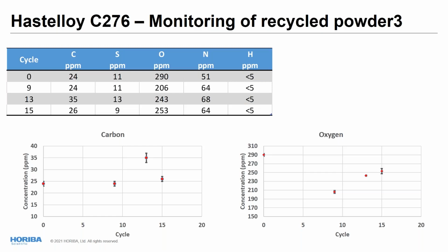There is an explanation. We needed to do some additional analysis, and we were not able to do them because we didn't have enough samples. But most likely what happens here, we may have oxygen at the surface. That is the contamination that disappears during the first cycles of the process. But the steady increase here is most likely an oxidation of the powder over time. And that is definitely something you want to monitor closely because sooner or later, it will affect the final part and the process itself.